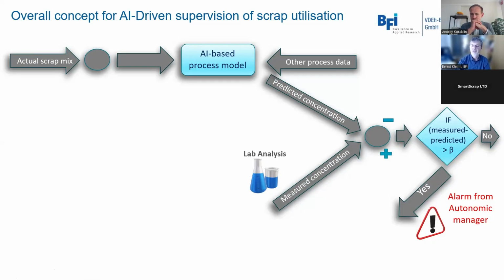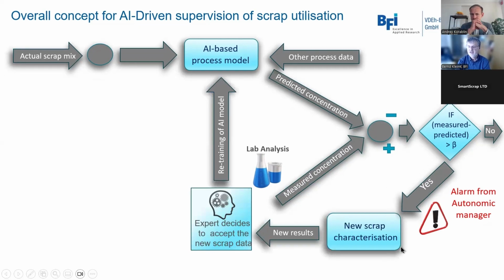We assume that the composition of the charged scrap mix is not as expected, and this means that we need to recalculate the composition of the different scrap types. So this is then done automatically. A new scrap characterization is performed. We achieve new results for the phosphorus or copper concentration of the different scrap types, and an expert decides to accept or to decline these results.